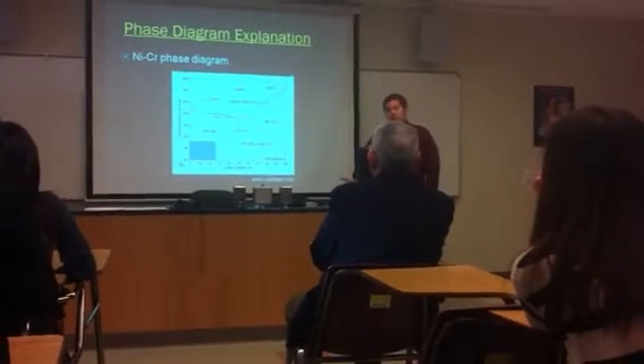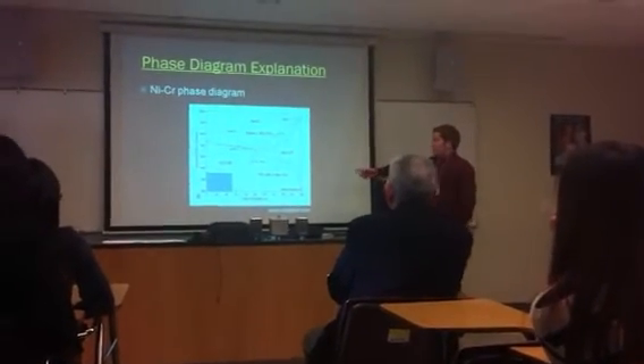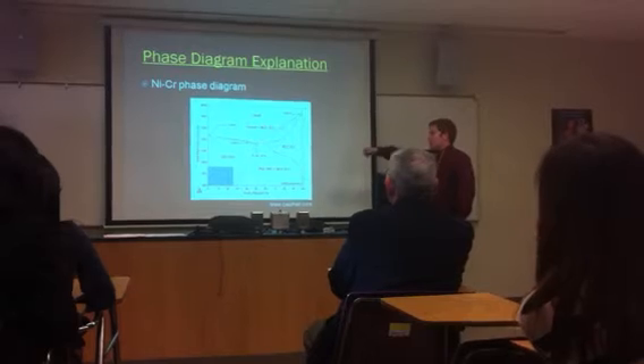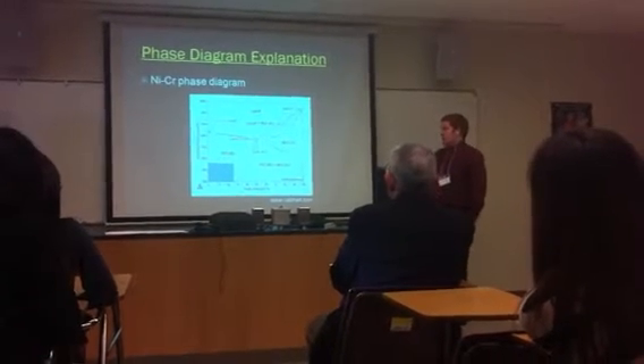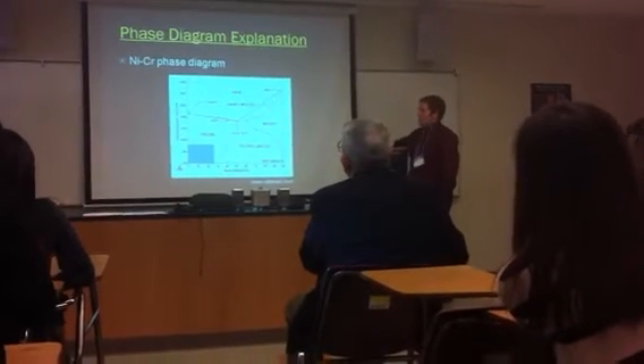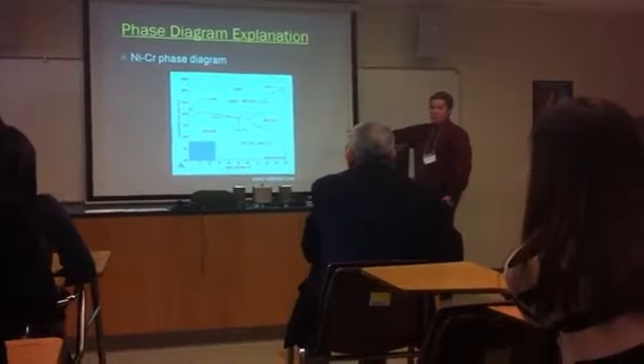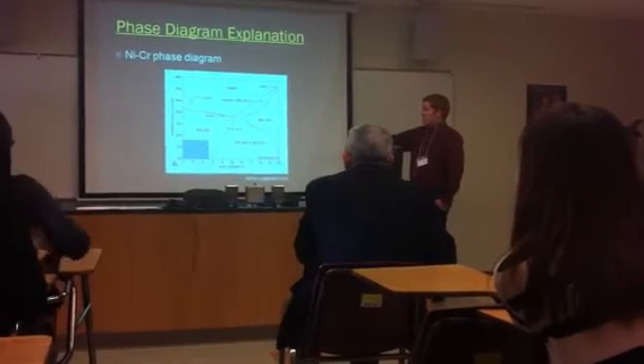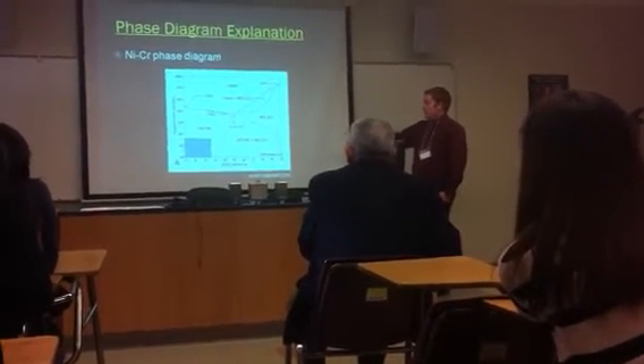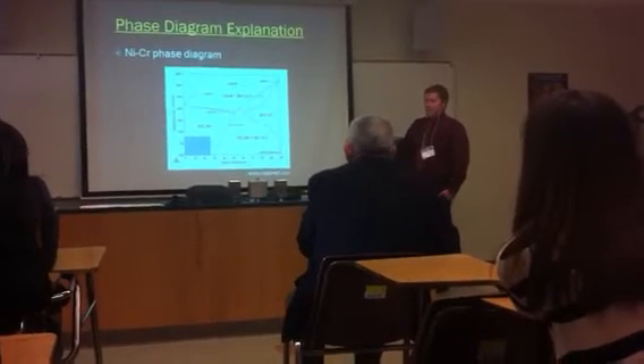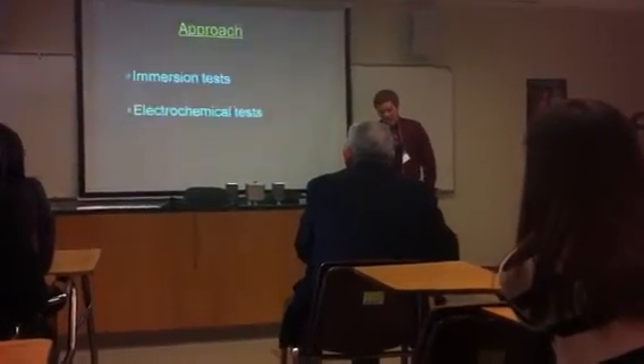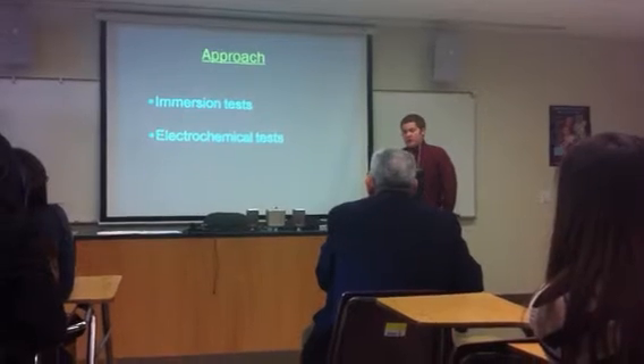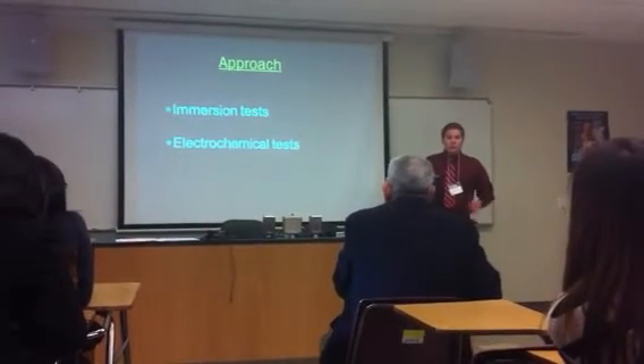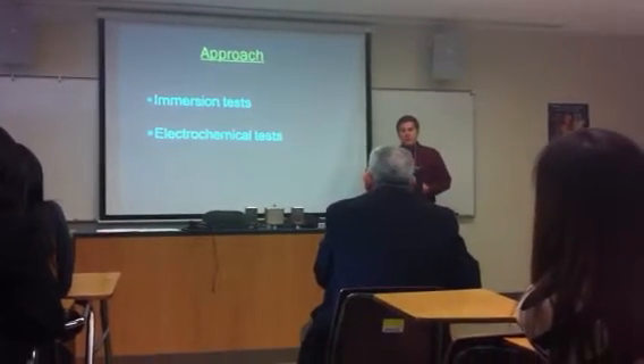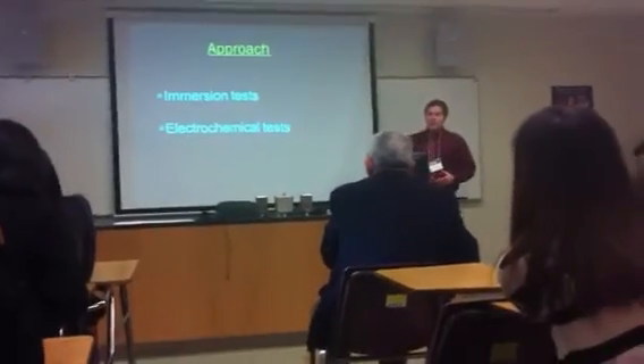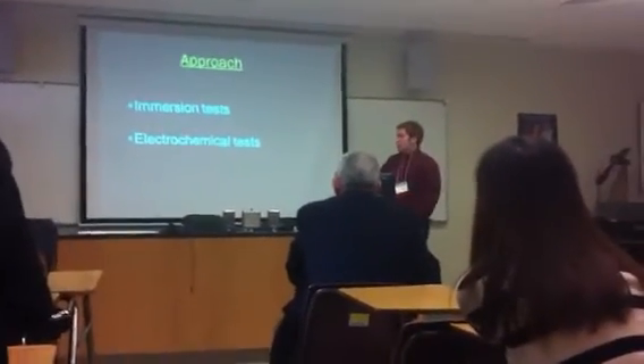And here's just a phase diagram of nickel chromium. On the y-axis, you see the temperature in degrees Celsius. The x-axis is the mass percent of chromium. And we'll be operating in the region outlined in blue at 900 degrees Celsius with mass percent of chromium from 0 to 25%. And it's the FCC phase of nickel. And our approach for this, like I said, would be immersion testing, which we're doing just small scale to get more information and see how this all works. Then we'll move on to electrochemical tests, which will be a much bigger scale process.